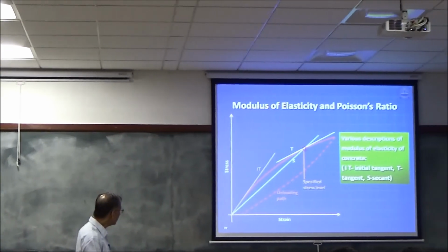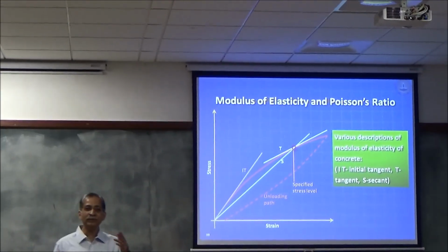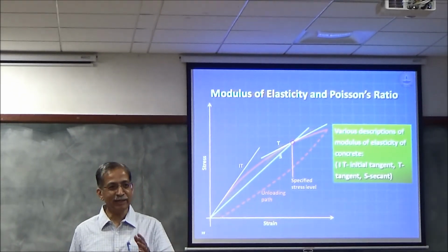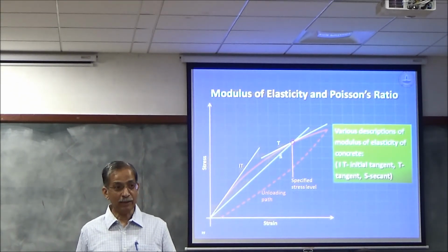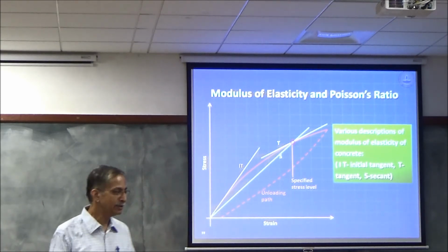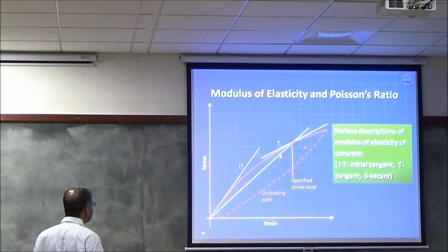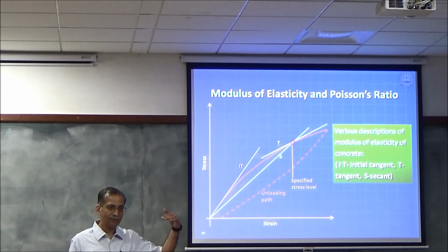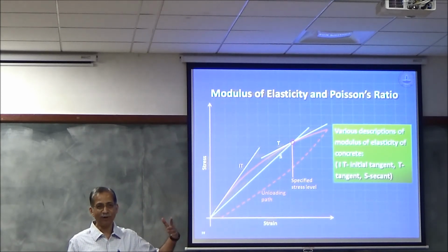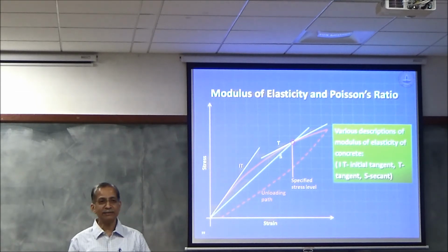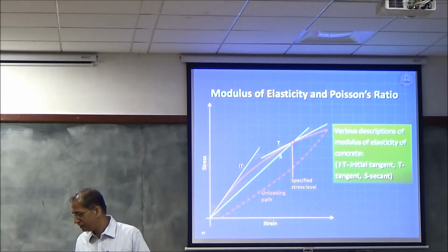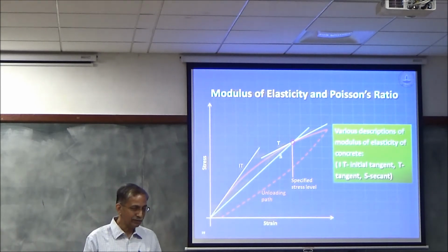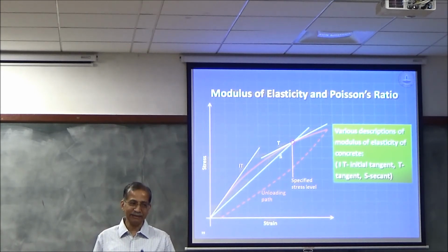Okay. So you will find that up to service loads, 1 kilo, 2 kilo, 3 kilo, 4 kilo. But large deformations, gone. You can't use the same thing. So usually this is taken at roughly 1/3 the ultimate strength of concrete. You're not supposed to cross that. You remember your old working stress method. Your allowable stress was roughly of that order. Factor of safety was 3 or 4: 3 in flexure, 4 in compression. Remember? So it's more or less straight then, right?